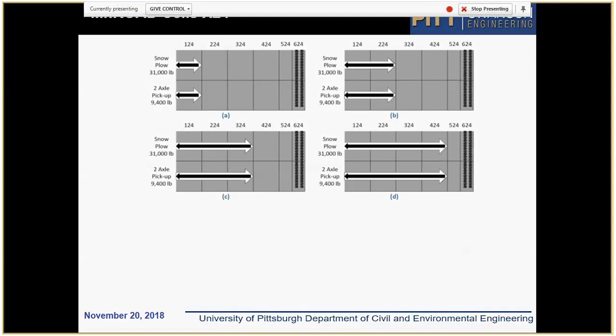So this slide shows the loading pattern. First, cell 124 was loaded, and the vehicles moved back and forth. After that, both cell 124 and 224 were loaded, and again the vehicles moved back and forth, and then 324, and in the fourth loading, all the sections from 124 to 424 were loaded. I need to mention that the sections were constructed from west to east, from 624 to 124, so that at the time when section 124 was loaded, the concrete was much more mature than the other sections.